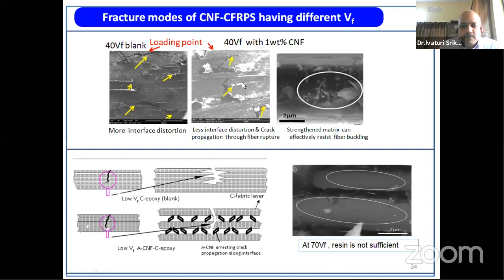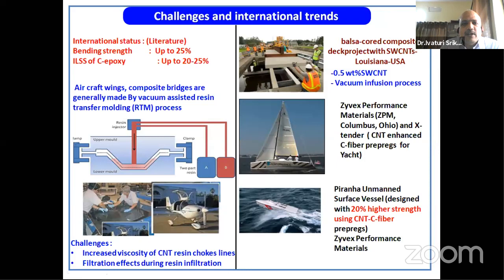So finally, what we found is, if you make only a 40 VF or 50 VF composite, then nanotubes or nanofibers can improve the strength. But that kind of strength values you can get if you directly make a 70 VF composite. But globally, people have made CNT composites with 10 to 25% improvement in shear strength and flexural strength.